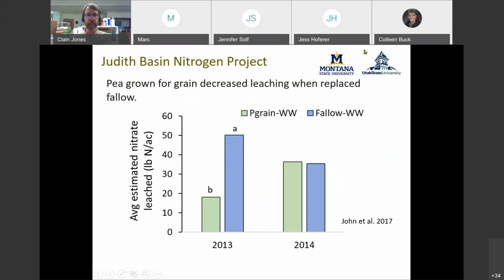A little closer to home, on a study that I worked on called the Judith Basin Nitrogen Project, here we compared a pea that was grown for grain, followed by winter wheat, with a fallow winter wheat rotation in both 2013 and 2014. And we plotted the average estimated nitrate leached in pounds of nitrogen per acre. So in 1 year of the study, 2014, there didn't seem to be a big difference between them. But in the first year of the study, the amount of nitrate leached in the fallow winter wheat system was 50 pounds of nitrogen per acre. That's a pretty big chunk out of maybe 80 pounds applied compared to only 18 that was lost in that pea grain winter wheat system. So again, both in Saskatchewan and here in Montana, decreasing fallow should decrease leaching.